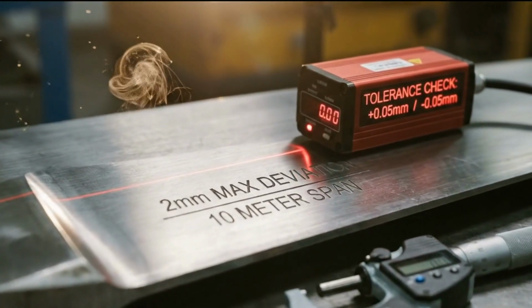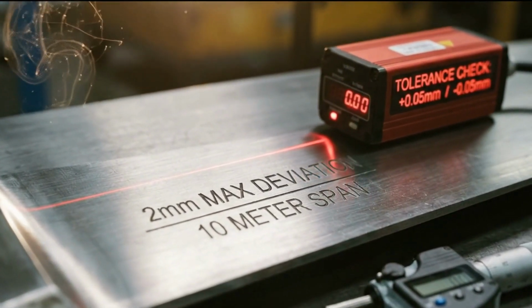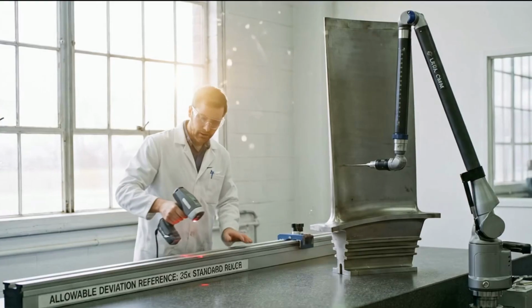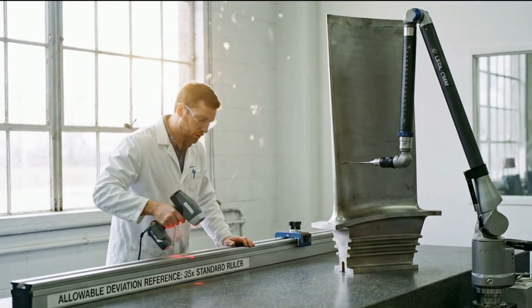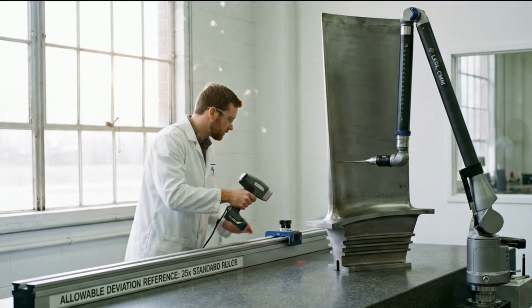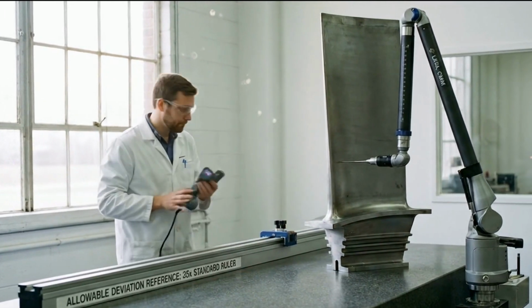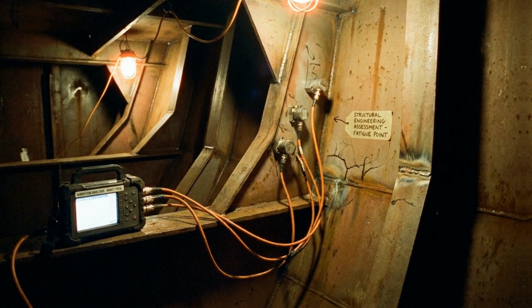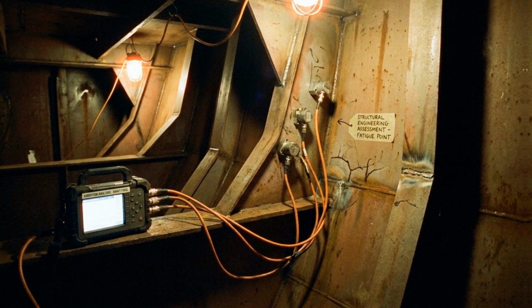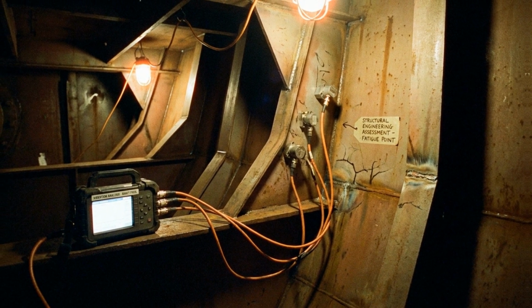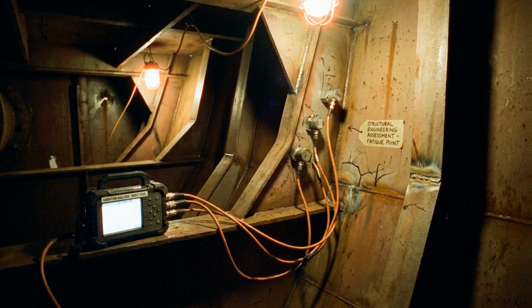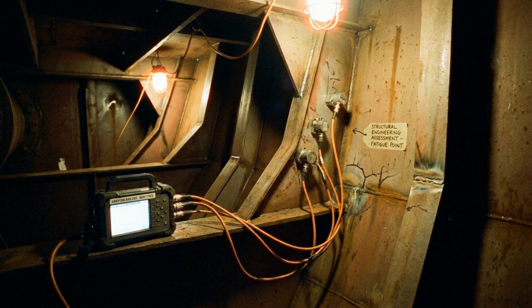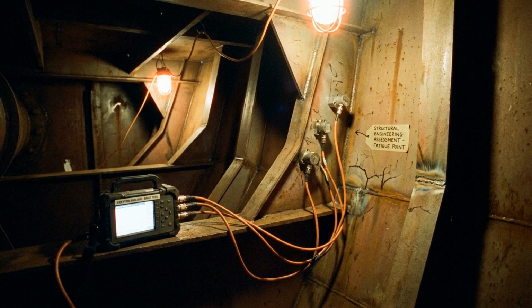The tolerance requirement across each blade surface is within 2 millimeters, across 10 meters of complex curved bronze. 2 millimeters of allowable deviation across a distance 35 times the length of a standard ruler. That tolerance exists because a propeller running out of balance or with incorrect blade geometry doesn't just perform poorly. It generates vibration at the shaft frequency that propagates through the entire ship's structure, fatiguing welds, loosening fittings, and in severe cases causing structural damage to the hull over time.